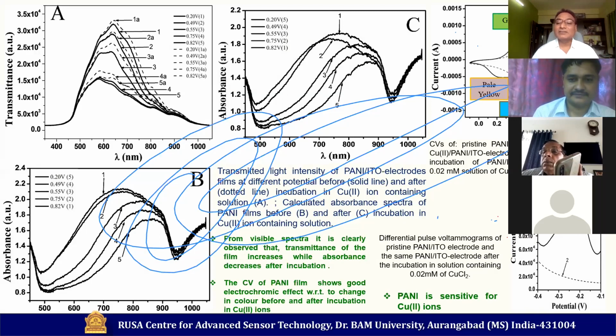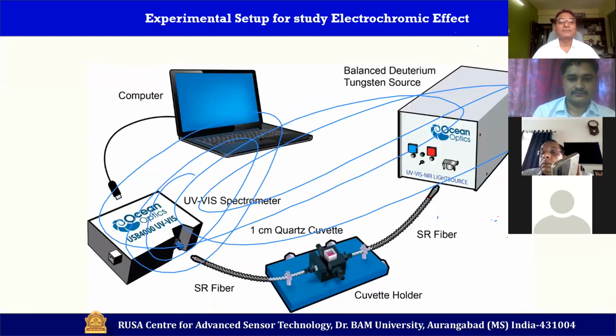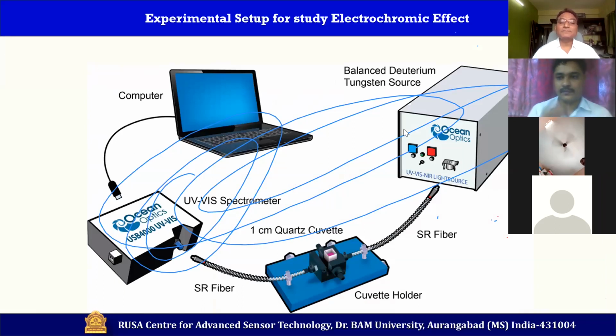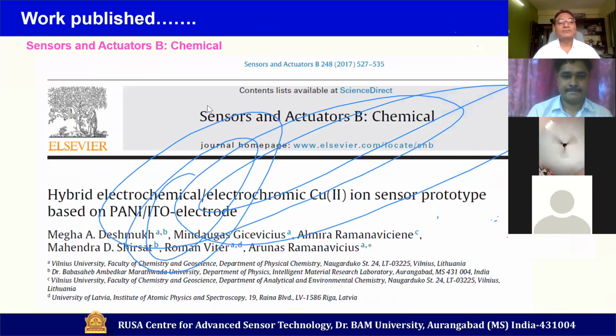You can see this is after incubation, and this is before incubation. Before incubation of copper ion, there was a flat curve. We did not observe any peak, but after incubation we could observe a very significant peak, right? And this was the experimental setup we have utilized for this study. And this work was published, as I mentioned earlier, in Sensors and Actuators B: Chemical long back.